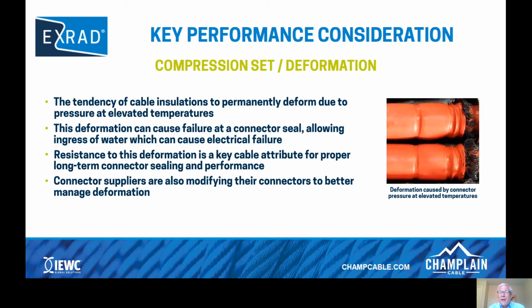The resistance of this deformation is a key cable attribute for proper long-term connector sealing and performance. Now, let it be known that not all XLPOs are created equal. Some have much poorer compression set properties than other XLPO insulations that have much better compression set properties. And what I mean by better compression set properties means less deformation. Connector suppliers are also modifying their connectors to better manage deformation. And what they're doing with their seal glands is using lower durometer materials, which will not deform the XLPO insulations as much.